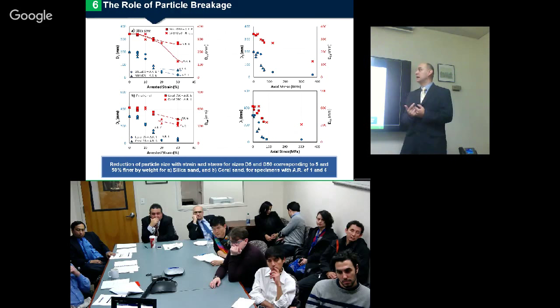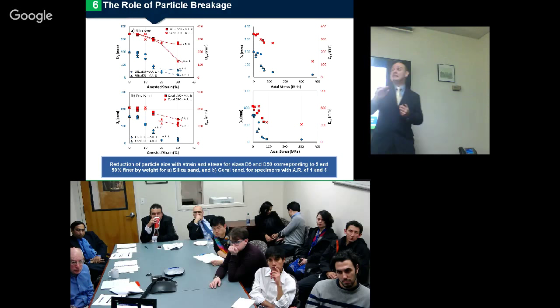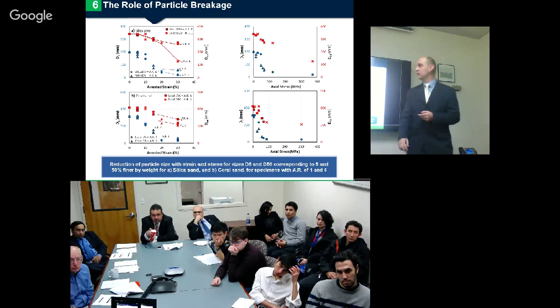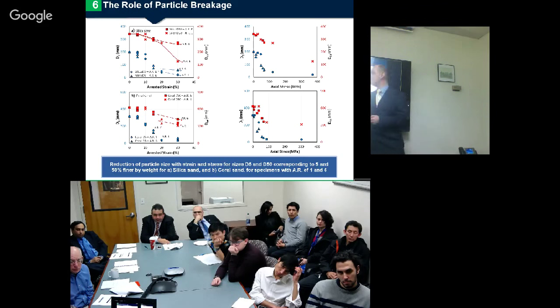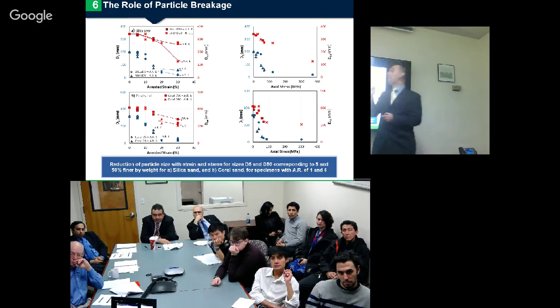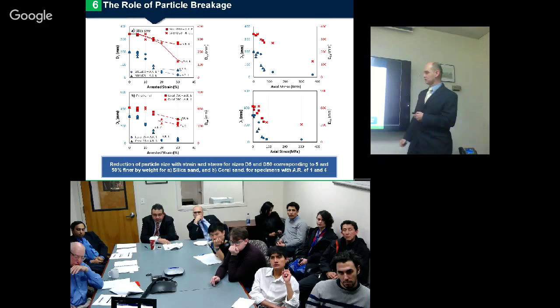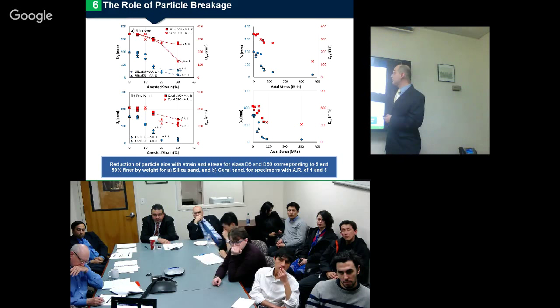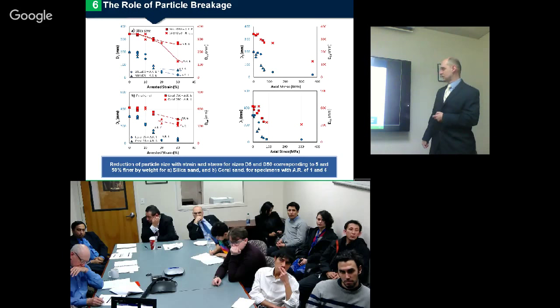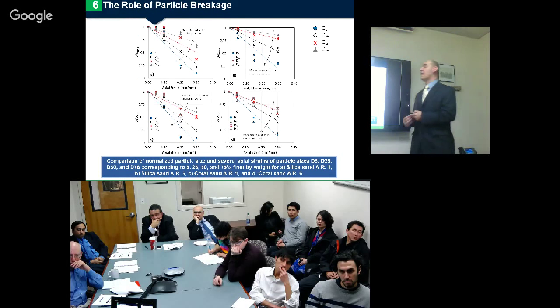And then we can see at what point of deformation the material starts experiencing more damage. Right after 10% of deformation, this curve changes its slope, and we can see more evidence of damage after this point. The same happens with the D50. Obviously, it's not going to break as much as the D5, but it will show some damage. Something similar is happening here: after almost 80 megapascals of stress, the damage is observed.